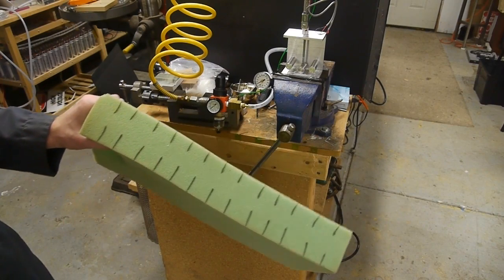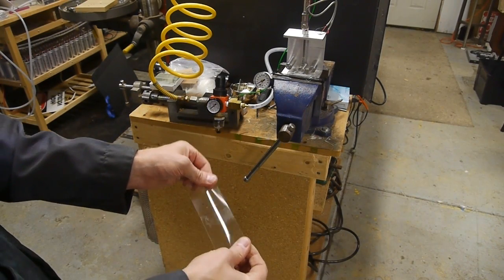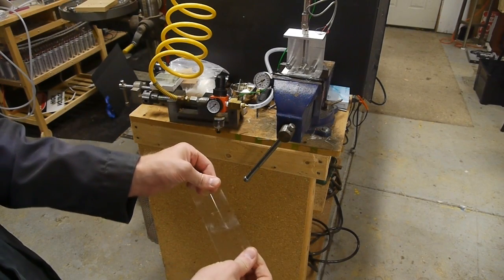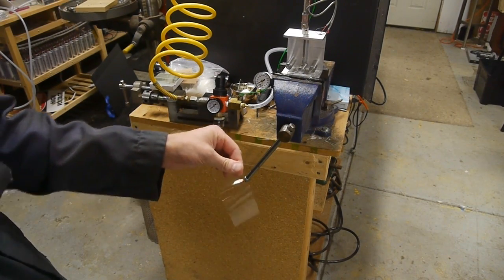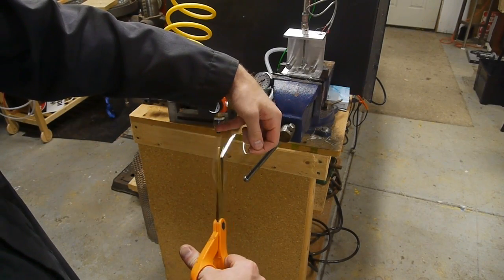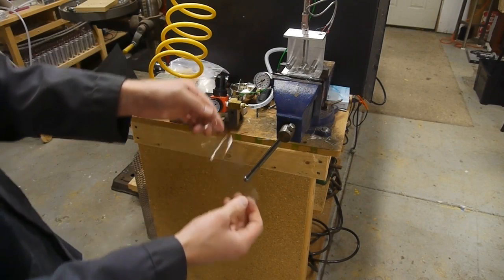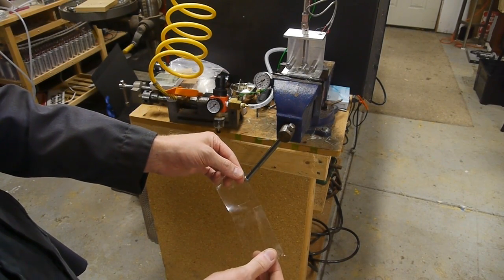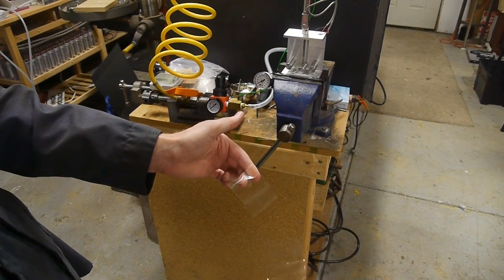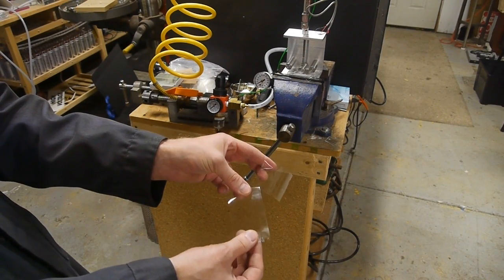Let me show you with a piece of packing tape. If I pull on the tape like this you know I can feel it stretching a bit but it's certainly not breaking, it's quite strong. However if I introduce a defect just by slicing it a little bit with a pair of scissors so that there's a cut in it, now you can see the defect, and then I just pull on it, there's no strength at all.